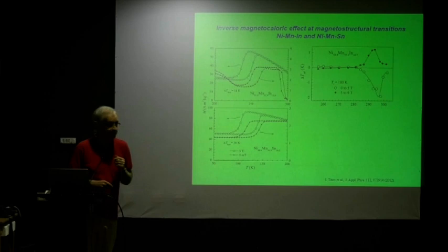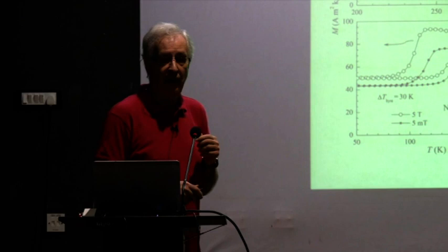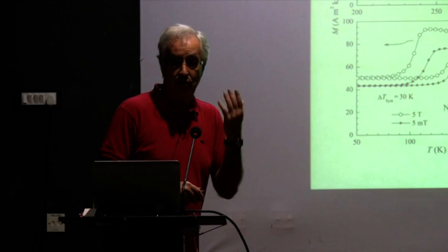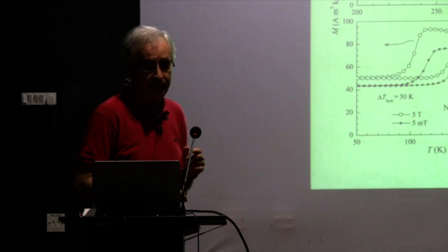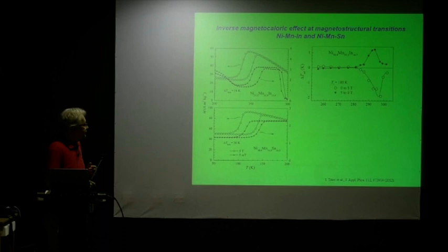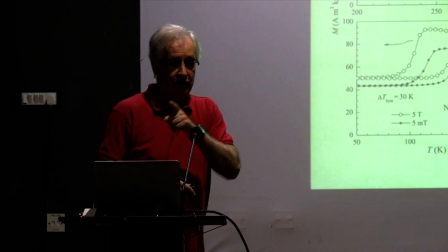If you go to the maximum over here, you have a maximum of about 2 Kelvin over here, but this maximum over here is about 1.2 Kelvin. So initially when you applied a magnetic field and you were in a state over here or somewhere, you had a large temperature change. And if you had no hysteresis, then you would have recovered this temperature change after waiting a long time, and this would have come up here, okay? But it doesn't, when you're going from the martensite state to the austenite state by applying a magnetic field,